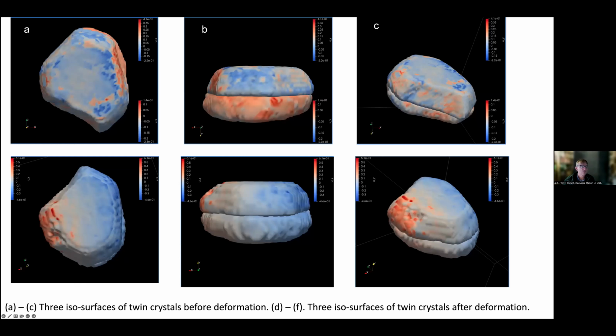So the top row are just 3 different views of the reconstruction phase map from the twin pair in the as-generated state. And then what you see below is the same kind of map, but after we poked at it. And you can see that in the one crystal, there's distinctly something going on here. So that's interesting, but again, looking at the outside surface.